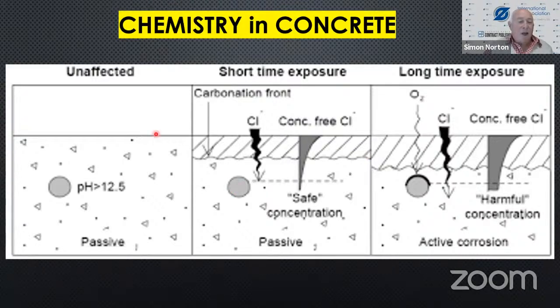However, going back to the amphoteric zinc, if you had galvanized your rebar, you would then find that as the carbonation moves through the concrete, the pH of the concrete will change, and the pH will come closer to a low pH. So in this particular case, zinc being amphoteric, if you galvanize your rebar, will react with a pH of 12 material. But equally, if there's an acid environment, because the pH lowers because of carbonation, you'll get a reaction. That's the amphoteric nature of zinc.